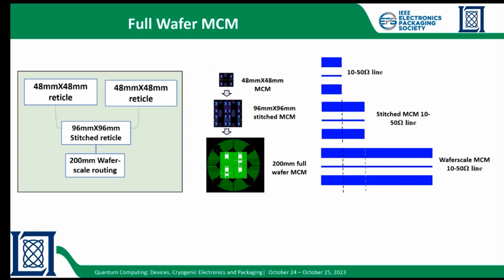So what will happen when a signal goes from single MCM to stitched MCM to wafer scale MCM? For single MCM, impedance controlled lines are within the MCM for chip-to-chip communication. For stitched MCM, impedance controlled signal lines have to travel from one MCM to the other through the stitch boundary. And then direct write wafer scale routing takes the signal from the stitch boundary all the way to the edge of the wafer. So it is important that when a signal goes from one end of the wafer to the other, through many stitch boundaries, there should not be any impedance discontinuity at the stitch boundary. So this is about wafer scale MCM.